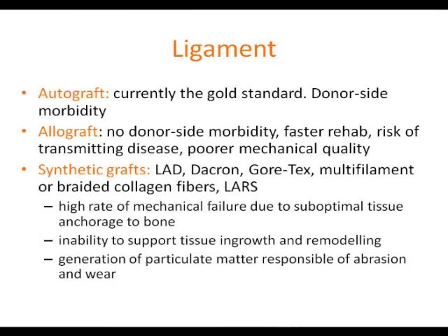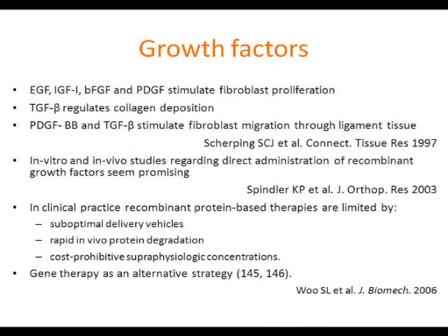have failed with a huge problem on the bone, and for the generation of particulate matter responsible for abrasion, wear, and bone lysis. So there is still a lot of things to do, a lot of investigation to do on the ligament. And again here, the role of growth factors, for me, my personal opinion, they are overrated and overused.